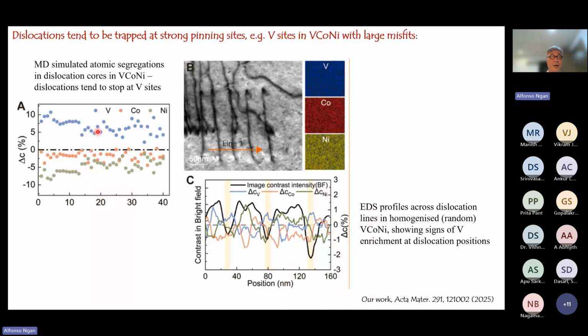So here, first of all, the left-hand side, A, is the MD simulated result. Through the MD simulation, and also we use Monte Carlo to stabilize the structure, to enable the structure to adapt to an equilibrium, we found that in this case, the dislocation cores are usually segregated with vanadium.